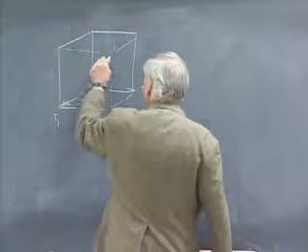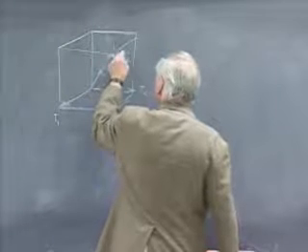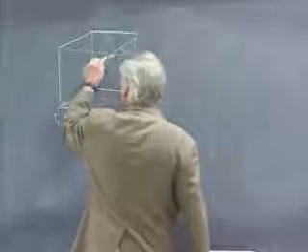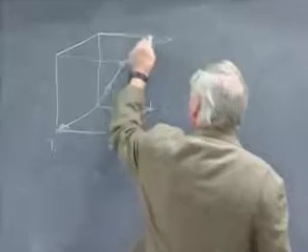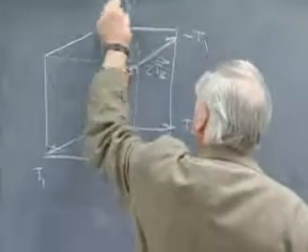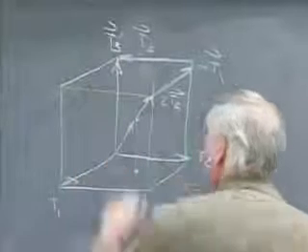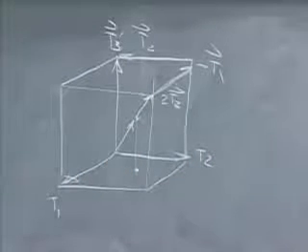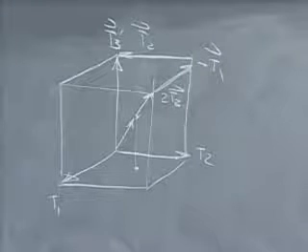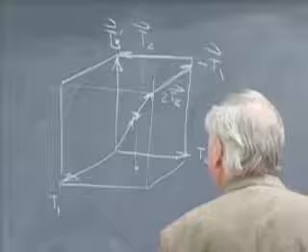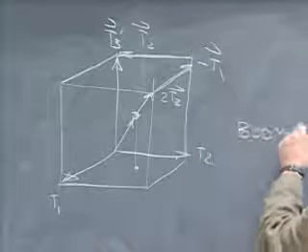And then if I go up two translations T3, and then subtract off T1, and subtract off T2, I will again have a T3 prime, which is exactly normal to the base of the cell. Okay, this is a type of lattice that you've come to know and love in the cubic system. This is referred to as a body-centered lattice.